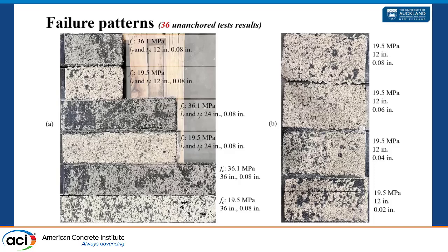For the lower concrete compressive strength, more concrete always remained attached to the FRP after debonding compared to the higher one. We observed similar phenomena for the thicker types: the thicker types had more attached compared to the thinner one. So that inspired us. The debond strength may not only correlate to concrete property or FRP property, but might correlate with the relationship between the two.